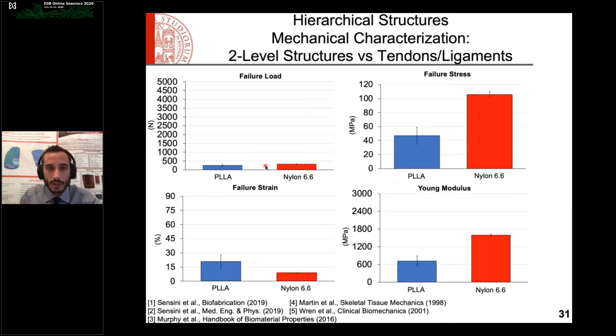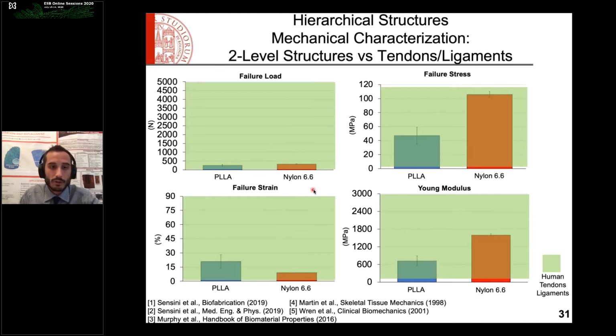Moreover, here I have matched the mechanical properties of the two-level structures and nylon 6,6 structures in terms of failure load, failure stress, failure strain, and Young's modulus with the typical average mechanical properties of tendons and ligaments reported in the literature. You can see that the range of mechanical properties of tendons and ligaments is very wide because they change in morphology, structure, and function.